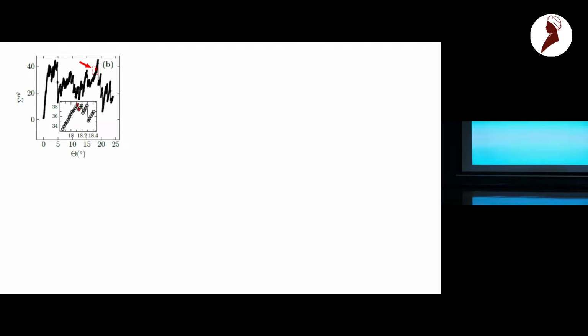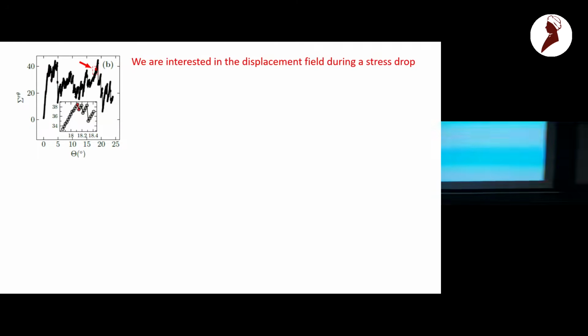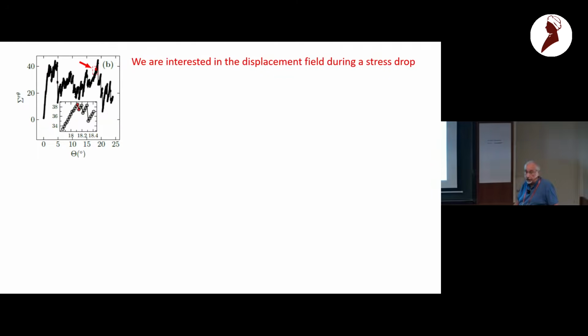Okay, so Couette geometry, and now when you do this, you measure the stress, and you've seen this many times. So the r theta component of the stress, which is the shear stress, the coordinates here are the angle and the radius. You have the usual thing that the stress is increasing at the beginning, looking sort of elastic, and then you have all these drops, the plastic drops. And what we want to understand is what happened at one of these drops. So we are interested in the displacement field during a stress drop. Why displacement field? Because it's measurable.